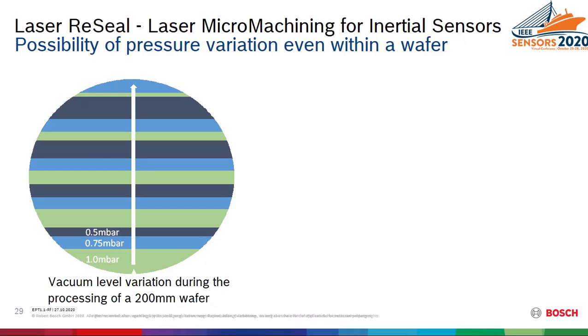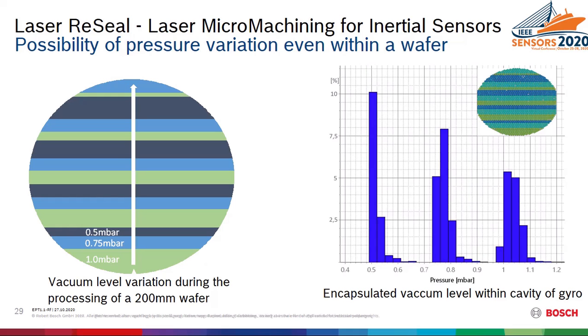Just for this conference, I prepared a 200mm wafer with 3 different encapsulated pressures, varying from 0.5 millibar to 1 millibar. Just to show you that we can do it. I varied the size of stripes from the notch region to the anti-notch region, keeping the 0.75 millibar stripe width constant and decreasing the width of the 1 millibar area. At the same time, I increased the width of the 0.5 millibar stripe from notch to anti-notch. On the right hand side, you see the actual data in an electrical wafer map.